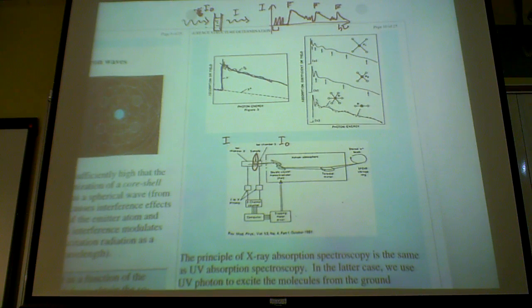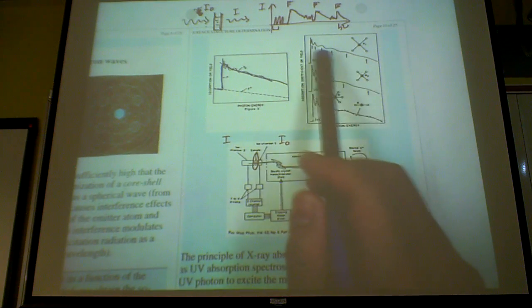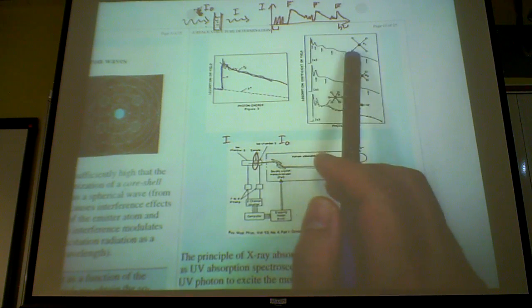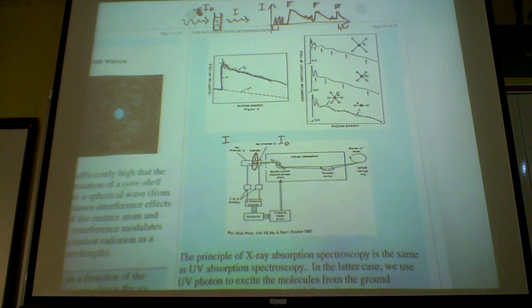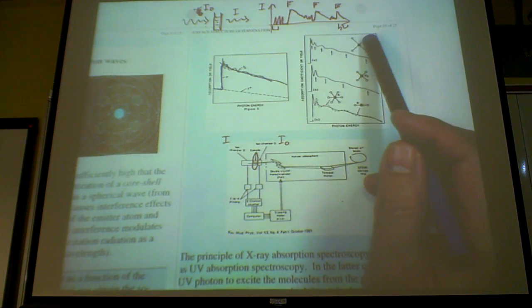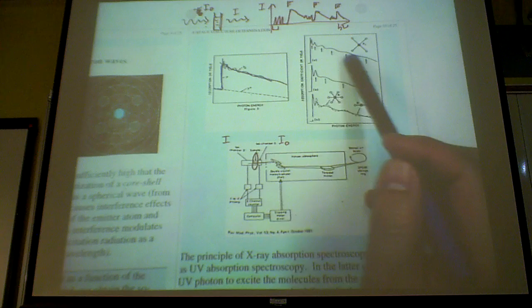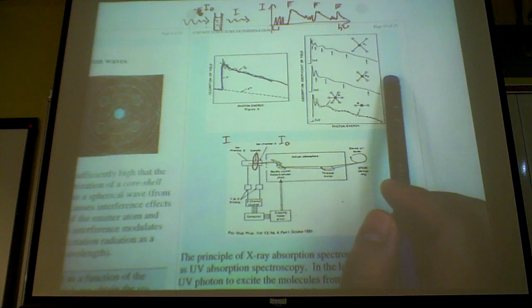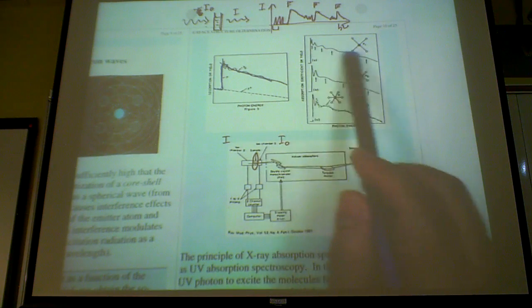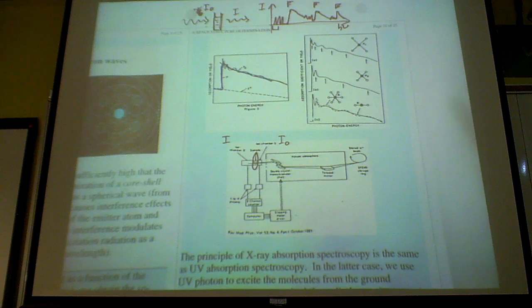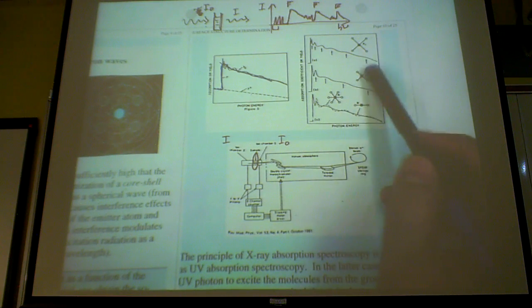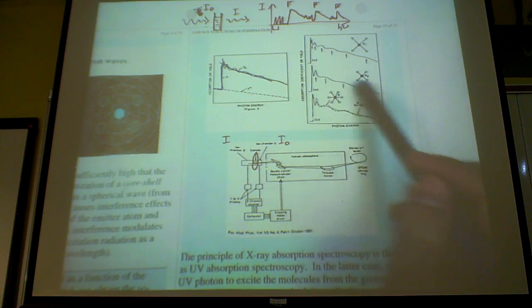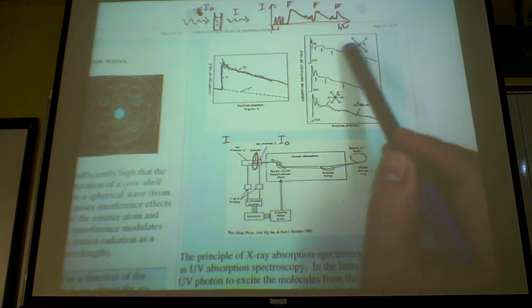The second thing they noticed is the periodicity, right? If you point out the peak locations of these, this periodicity seems to depend on the bond length. The larger the bond length, the closer are these peaks. They don't seem to lie in a regular fashion, it's sort of a semi-regular fashion. They have a wiggle, but the wiggle seems to be spreading out. If you look at shorter bond lengths, these wiggles are spreading out further than the one with longer bond length.